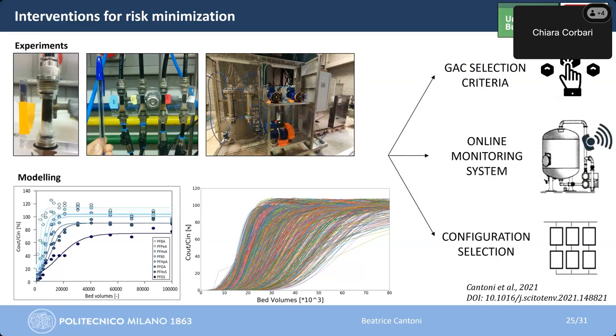Then knowing the saturation curve for each compound, here are just some examples, the dots are the experimental results. We then fit models to the curves, and then we understand what the main parameters related to the compound, the activated carbon and the water quality are that affect the saturation curve behavior. And then we are able to simulate other conditions that we couldn't test. This is useful to select the best activated carbon or, for example, to evaluate the configuration of the filters.